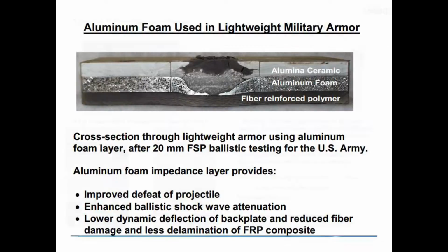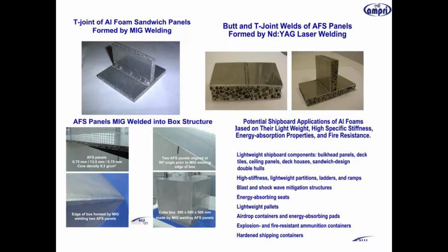And this can be welded also. These foam materials can be welded, and they can be given any kind of shape. So with this lot of application, we at CSIR tried to develop this material through a casting technique. And a report says that if this foam material replaces the conventional material in a ship, it can reduce the weight of the ship by 1,000 to 10,000 tons. So the ship would be much lighter.